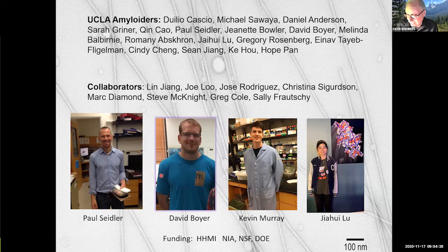And then in terms of energy calculations, I think our energy calculations are quite approximate. I think all energy calculations are quite approximate, including ours. We can't at present use the Rosetta programs, for example, because these cryo-EM structures are not extremely accurate. So in the final models there will be some overlap of non-covalently bound atoms, so that if you calculate the Rosetta energy, it's just huge and unrealistic.